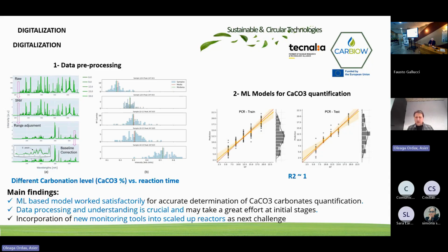I mean, after carbonation you get a new amount of carbonates, and that is the same as the CO2 fixation. You can extrapolate. So the lab classic approach by calcimetry and TGA, thermogravimetric analysis, and the prediction of the model were quite accurate, with some statistical data that gave us a good accurate value, and we were very happy with this. Now the challenges are to scale this up and to integrate it with an industrial reaction process, which is not easy, of course.